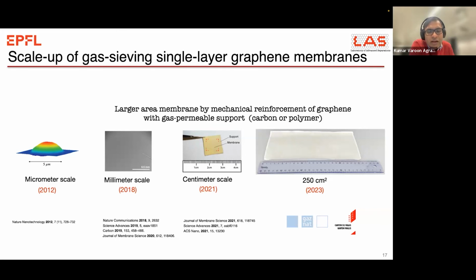This was by making sure the graphene doesn't break, and we came up with an out-of-the-box idea. This idea is essentially taking graphene and reinforcing it with a support so that it doesn't break. Usually in the field of membranes, people put the selective layer on top of a support. Here we were putting the support on top of the selective layer, and that essentially allowed us to prepare these membranes without having them break. Since then, we have successfully been able to make centimeter scale membranes.